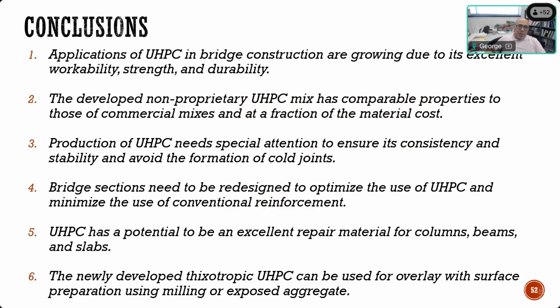When you produce UHPC, you need to give it some additional attention. It's not as easy as it is for conventional concrete, because there are more steps. It takes longer time, with some special sequence, but most important, you need to make sure it's consistent, stable, with the fibers well distributed, and avoid having cold joints, because if you have a cold joint, you lose the advantage of the fibers being a tensile reinforcement across this joint. So it needs to be continuous casting.